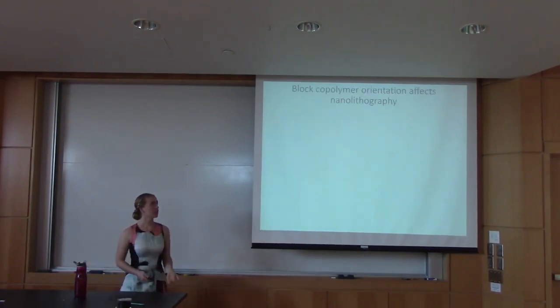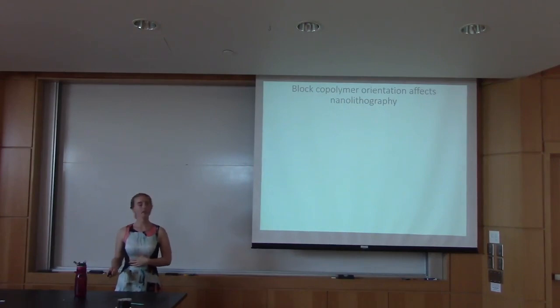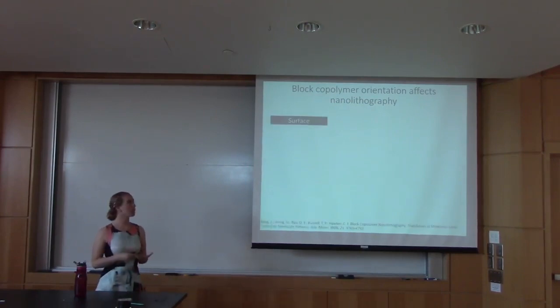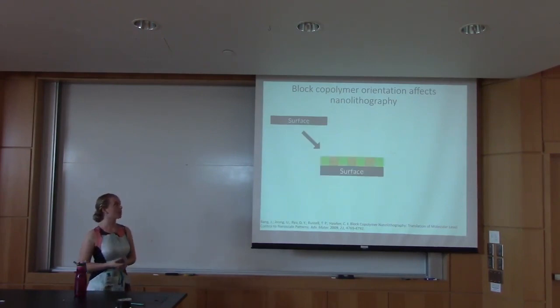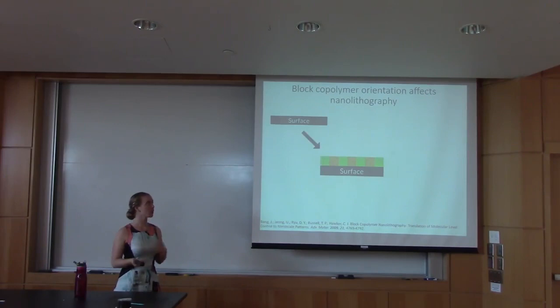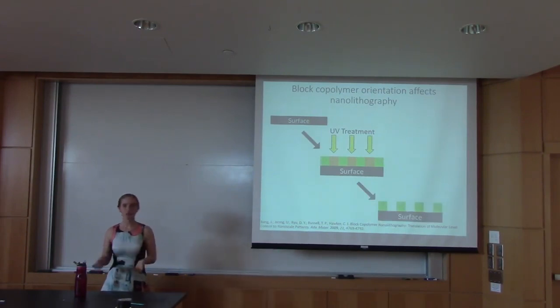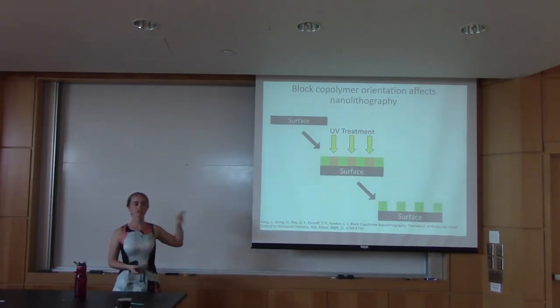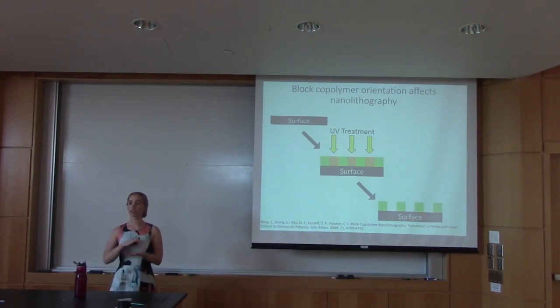So the way that we use these polymers for this nanolithography and for printing the circuits is by starting with a surface. And with that surface, we add on top our block copolymer, so our orange, green, alternating. And then we add our UV treatment. It preferentially gets rid of one of the polymers, so the orange polymer in this instance, and then we're left with this pattern. So this is actually a side-on view, whereas a couple slides ago when we talked about nanolithography, that was a top-down view.